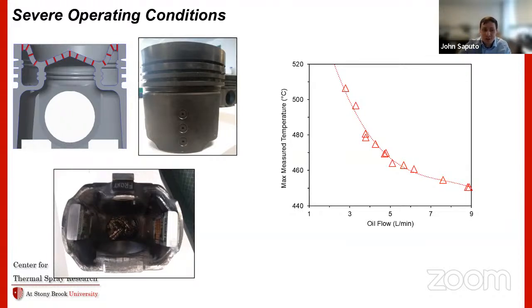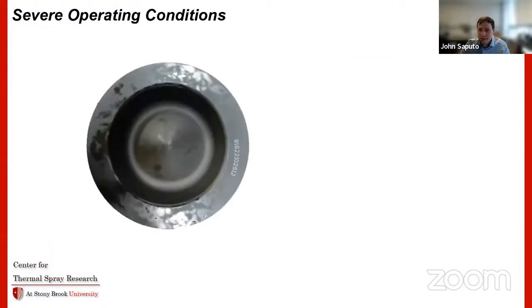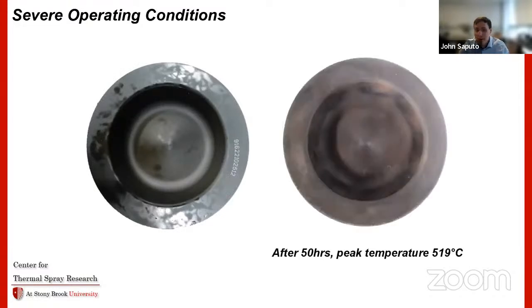So you can basically just shut off the oil that normally cools the piston and see how the temperature gradually climbs up. They're able to push things to about 515, 520 degrees Celsius, which is on the order of what people are expecting these increased pressure increments to push temperatures to in these systems. So that's great. You can take a piston out of this, put an uncoated piston in the system. They'll go in looking something like this and come out after about 50 hours looking something like that. So this is with no coating. This is just a bare steel piston, and they tend to rapidly oxidize.